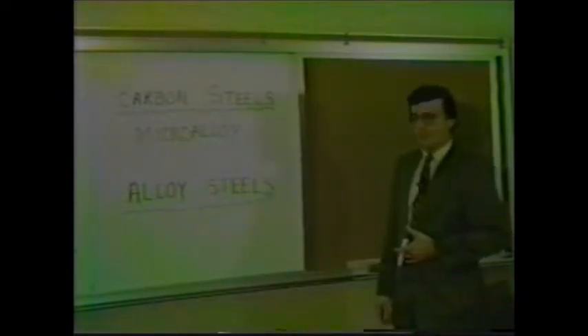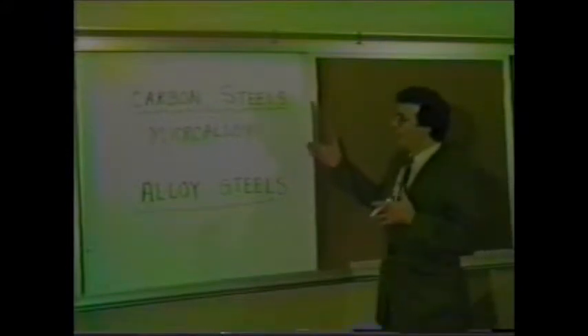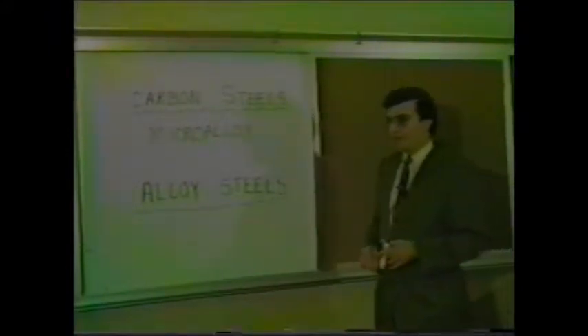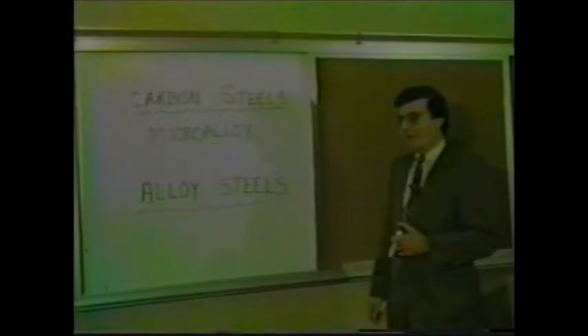Microalloyed steels are characterized by increased strength and good ductility while still in the hot-rolled condition, as opposed to cold drawing. The strength of microalloyed steels is gotten by putting nitrogen in the steel in combination with vanadium, columbium, or titanium. Another group of elements that can also be placed into microalloyed steels are nickel, chromium, or molybdenum, sometimes copper and zirconium also. But the amounts of these elements are nowhere near those for alloy steels. Again, it's just to increase the strength of the steel in the hot-rolled condition.